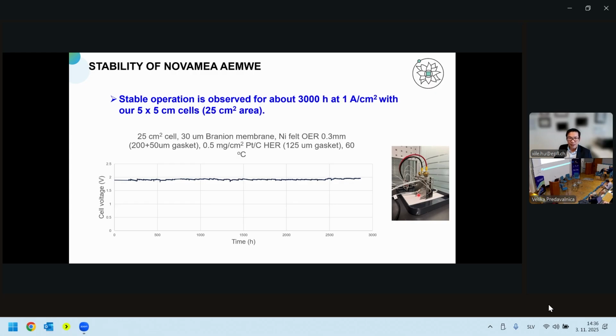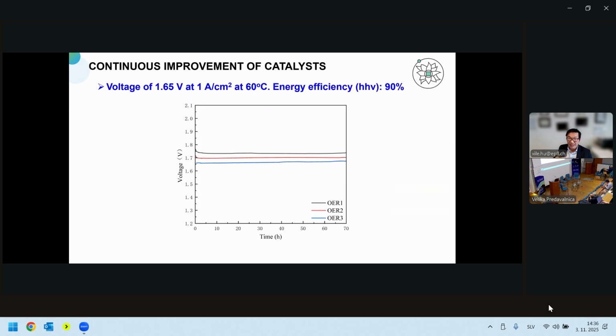We are also continuously improving our catalyst. For instance, we recently saw a third generation of our OER catalyst, where we can actually do it at 60 degrees. We can achieve 1 amp at 1.65 volt. And if we like a good number, and we typically like to have a high number, so we take the high heating value of hydrogen. And so if you calculate the energy efficiency, that is actually 90% energy efficiency. And this is real efficiency, obviously. And so we need to increase it from 70 hours to 70,000 hours, obviously.